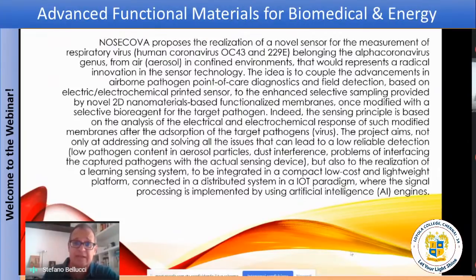And the idea is very new because it couples the advancement in airborne pathogen point-of-care diagnostics with the field detection based on a printed electrochemical sensor, pretty much like the one I showed you 2 slides ago, together with the enhanced selective sampling that is provided by what? By the use of new 2-dimensional nanomaterials like graphene, but not only graphene, transition metal dichalcogenides like molybdenum disulfide or hexagonal boron nitride. All of these allow us to create a functionalized membrane by putting a selective bioreagent that is able to react to the targeted pathogen onto the 2-dimensional material.